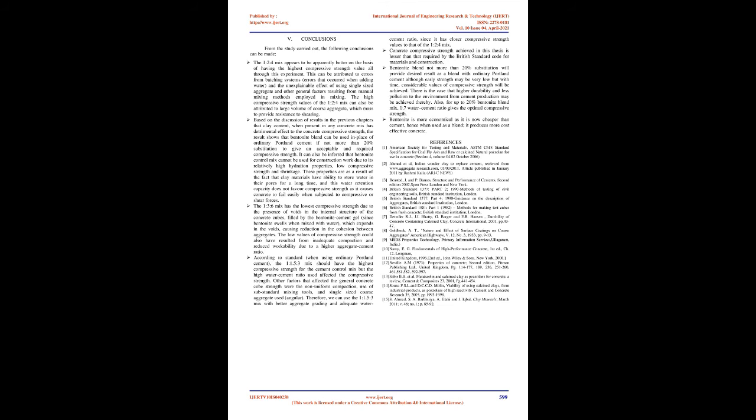These properties are a result of the fact that clay materials have the ability to store water in their pores for a long time, and this water retention capacity does not favor compressive strength as it causes concrete to fail easily when subjected to compressive or shear forces. The 1:3:6 mix has the lowest compressive strength due to the presence of voids in the internal structure of the concrete cubes, filled by the bentonite cement gel, since bentonite swells when mixed with water, which expands in the voids, causing reduction in the cohesion between aggregates.